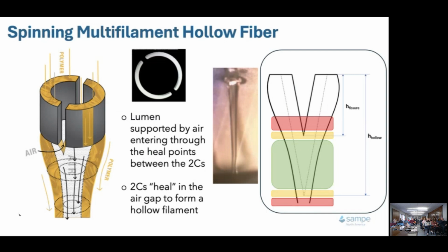We're spinning them with shaped spinneret technology. We essentially spin a left and a right side of the fiber, which when it passes through that air gap, those two sides come together and heal. As they heal, they create this pocket at the top, which is pulling air into the inside of the fibers, almost as if it's continuously blowing a bubble, but it's preventing a vacuum from the filaments from collapsing. The length of the air gap is a big player in that. This is an actual image of a hollow fiber being formed, and you can see the two walls in that microscopic image.